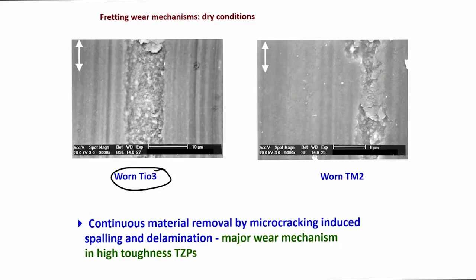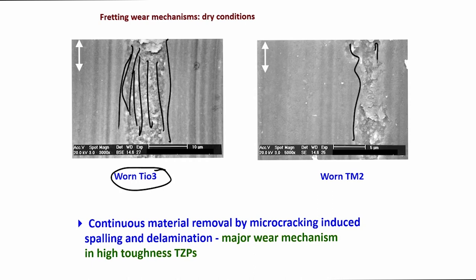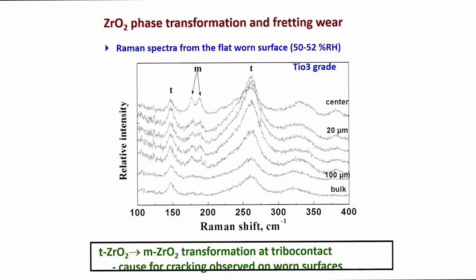Now, in the Tio3 ceramic also, you can see very clear spalling, like a couple of groups of the abrasive grains are simply spalled off, and that is the case for this TM2, that is the TZ mixed powders, and there again that leads to spalling and delamination in this particular high toughness TZPs. Now, as I said before, the tetragonal to monoclinic zirconia transformation leads to toughness increase around the crack tip.